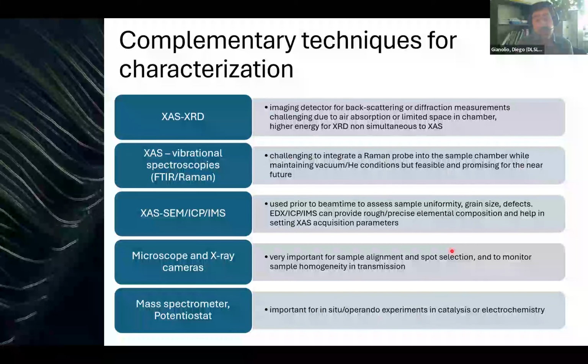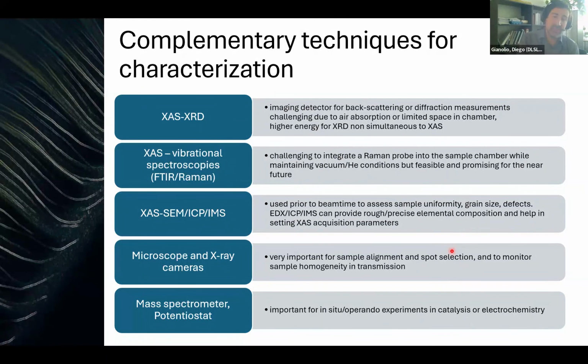And then the other problem is that if you want to measure XRD in transmission through the sample, ideally it would be easier to do it at higher energy. And so you would move to a higher energy to collect the XRD and then move again to the lower energy in the tender X-ray range to collect XAFS, but in this case it wouldn't be simultaneous.